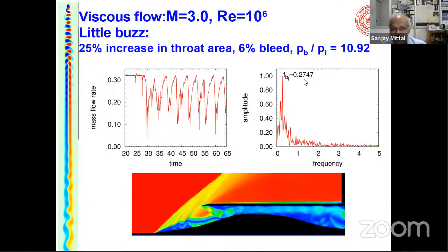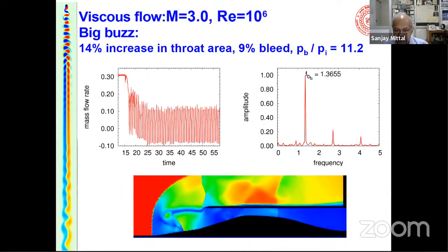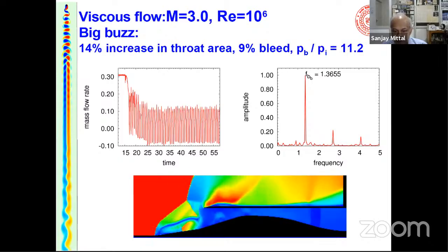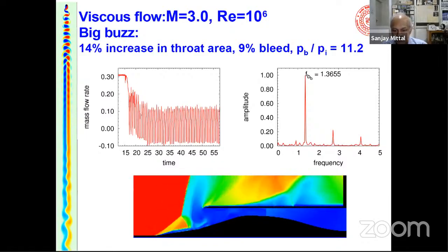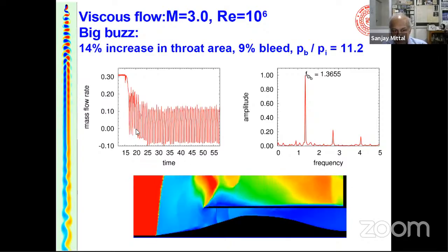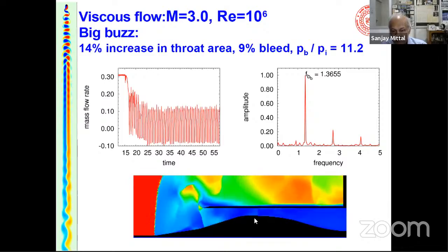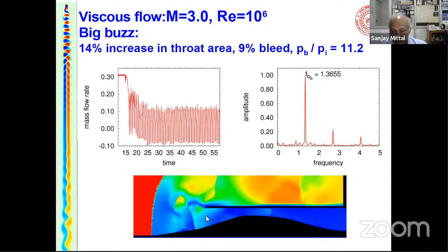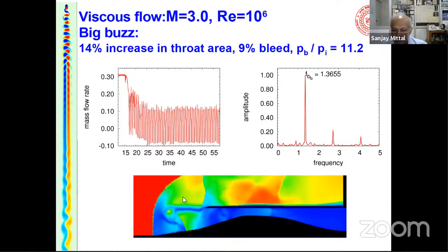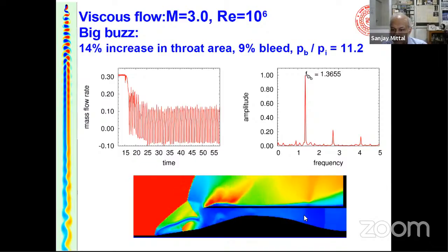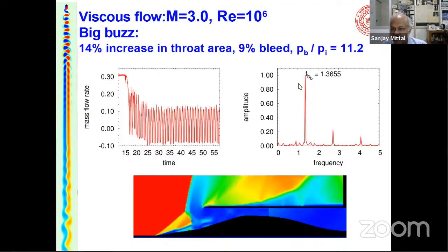I'll show you an example of an even more catastrophic buzz, which is called the big buzz. So here the shock systems are extremely strong, as you can see. And there is even more massive flow separation. So these shocks are going back and forth. So the engine fills up, then it empties again. And in fact, if you look at the mass flow rate, then you can in fact have a negative mass flow rate at the throat, wherein part of the cycle, the flow goes downstream, and in another part, it actually spills over and goes out of the engine. So this is a big no. You do not want to use this in a real engine. That's bad news. This one has a fairly large frequency, okay? And this could be of the order of several kilohertz.